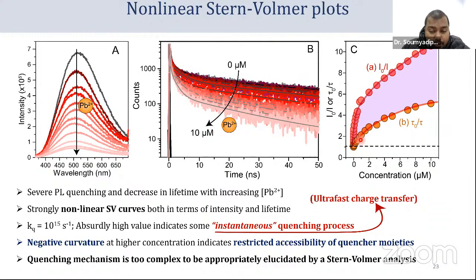And the quenching constant is absurdly high. It's around 10 to the 15 per molar per second. So what is going on? And you can see if you plot fluorescence intensity ratio or tau 0 by tau, both have nonlinear behavior in the Stern-Volmer plot. So basically, the quenching mechanism here is very complex. It's not as simple as that.